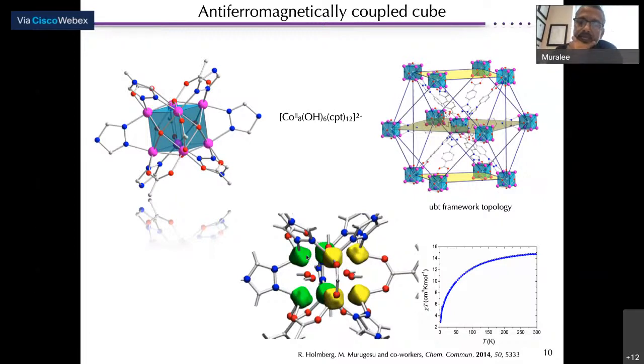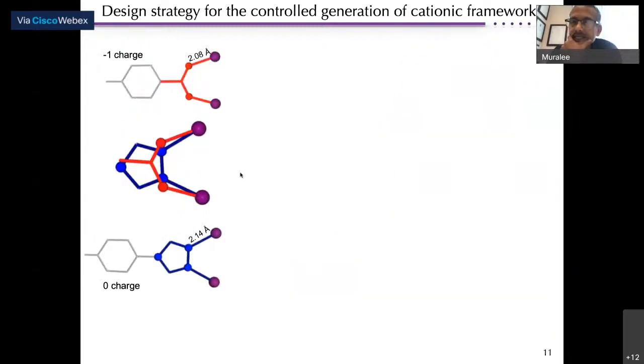By then, we realized that we were missing an interesting point of this asymmetrical linker, which is basically that if you take a carboxylate and look at these metal oxygen binding distances, they are very similar to the triazole metal nitrogen binding distances. And the bite angle is also very similar. But one key difference is the charge. A carboxylate brings -1, whereas a triazole based linker brings a 0 charge.